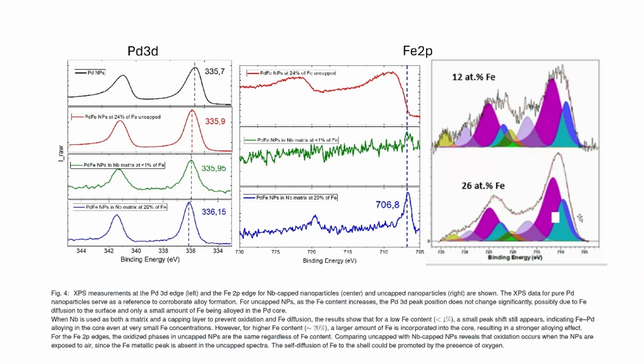In uncapped nanoparticles, increasing the iron content did not cause a significant shift in the palladium 3d peak. This suggests that the iron may diffuse to the surface, so only a small amount of iron could be alloyed into the palladium core. And when we cap the nanoparticles with niobium, which also serves as a matrix to prevent oxidation and iron diffusion, the results were different. For low iron content, by which we mean below the resolution limit, 1% at most compared with palladium, we saw a small peak shift, indicating that an iron palladium alloy is present even at very small iron concentrations. For higher iron content, in our case around 20% of iron, more iron was incorporated into the core and the alloying effect was stronger, so we saw a larger shift in the palladium peak.